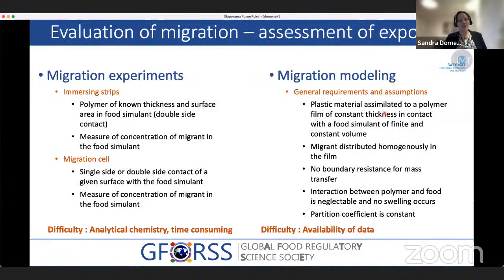So these situations need to be evaluated, and this evaluation is on the ground of all the migration testing which is asked for by the different legislations of the world, and which is going to be explained in the presentation after me. So there are two different possibilities to evaluate. Either you do an experiment where you immerse your strip of polymer and then measure the concentration of the migrant in the food simulant. You can also use a migration cell and do the same measurement.